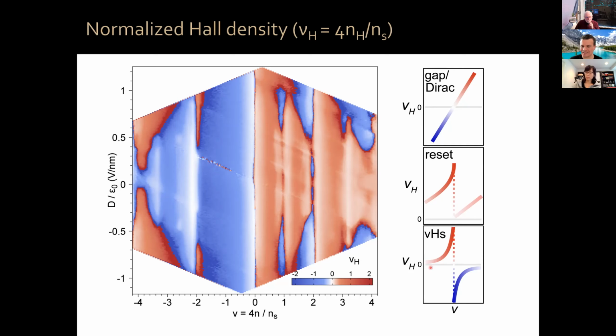Okay, so in these cases, your normalized Hall density flips sign but diverging at the sign change. Okay, so you can, for example, go from light blue to dark blue, abruptly switch to dark red, and then light red. Okay, this is something, because at the Van Hove singularity, your Rxy goes smoothly through zero. Your Hall density, which goes as 1 over Rxy, diverges and flips sign. Okay, this is something that you can see, for example, here. You go from light blue to dark blue, abruptly changes to dark red, and then lighter red. Okay, and it happens also here, and it happens in various places.